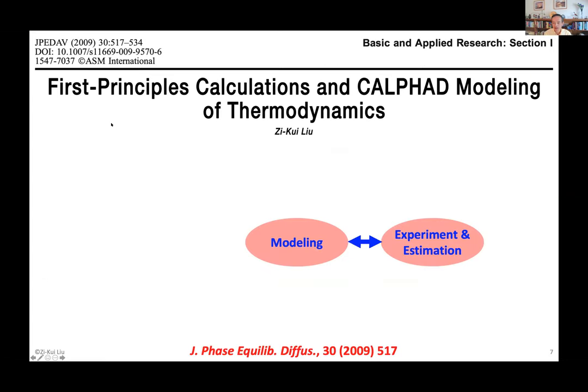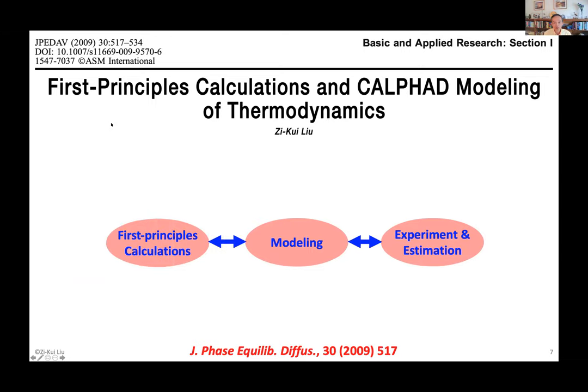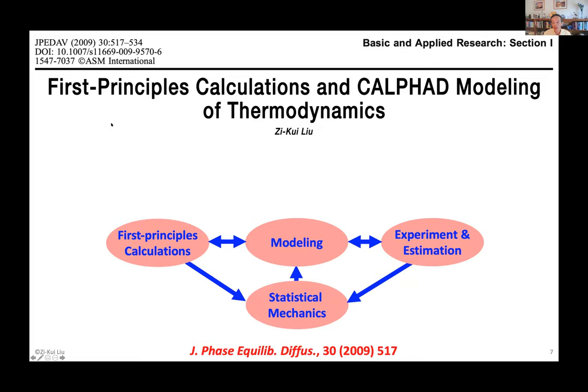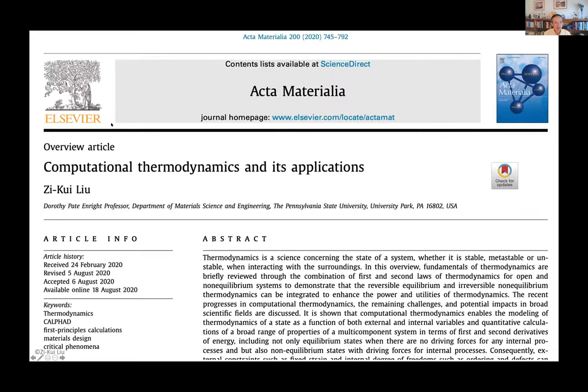We did modeling and experiment — that's how we have done it for at least 30 of the last 50 years. Then first-principles calculations became very powerful, becoming user tools, allowing finite-temperature statistics. We can get more data and enhance the power of CALPHAD databases. As I discussed in a paper I wrote last year, in addition to thermodynamic stability, we can actually talk about a lot of other properties — cross phenomena like Seebeck coefficient, transport properties, and even mechanical properties — because if we can understand the internal state variables, all these properties are related to them. If you can define it, you can calculate it.